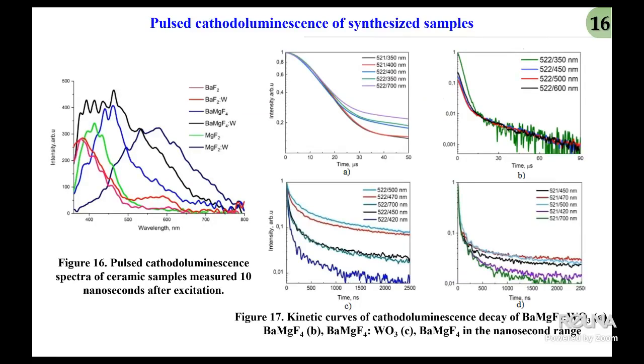This slide presents the integral cathodoluminescence spectra. Figure 16 shows pulsed cathodoluminescence spectra of ceramic samples measured at 10 nanoseconds. In figure 17, we see kinetic curves of cathodoluminescence, with and without tungsten ions.